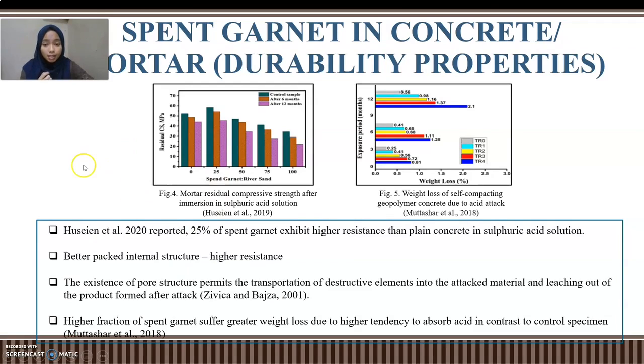You can see from these two figures, this mortar residual compressive strength after immersion in sulfuric acid reported by Hussein et al. 2019, and this weight loss of self-compacting geopolymer concrete due to acid attack reported by Muttashar et al. 2018. Okay, Hussein et al. 2020 reported 25% of spent garnet as having higher resistance than plain concrete in sulfuric acid solution. The integration of the exact quantity of spent garnet will be able to better pack internal structure that will lead to the higher resistance of the concrete and the mortar.